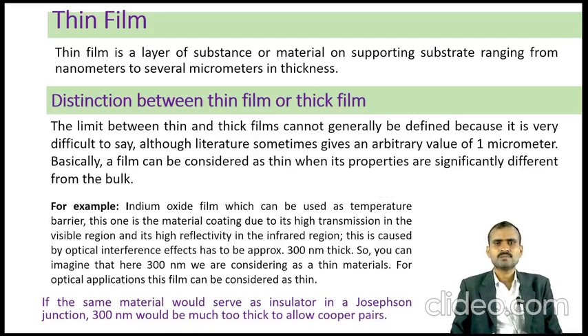For example, consider an indium oxide film which can be used as a temperature barrier. This is a material coating due to its high transmission in the visible range and its high reflectivity in the infrared region. This is caused by an optical interference effect, and the film has to be approximately 300 nanometer thick. So, you can imagine that here we are considering 300 nanometer as a thin material. For optical applications, this can be considered thin.